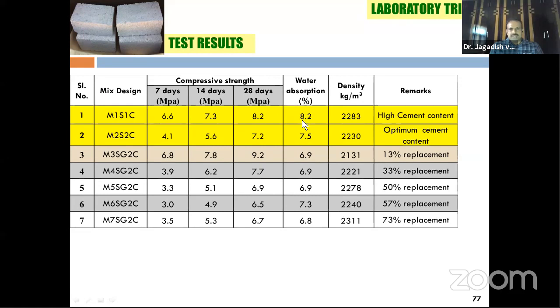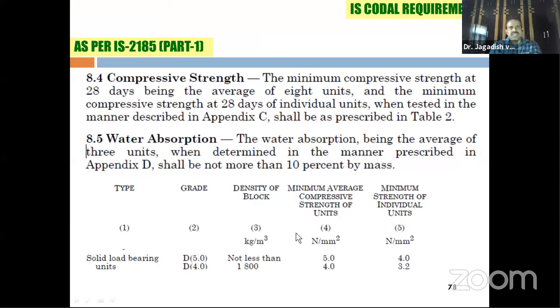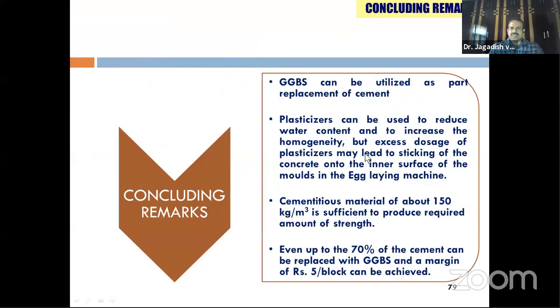Water absorption is also less than 10%. Density is more than 1,800 kg per cubic meter. And strength is also more than 5 MPa, even after replacing 70% of cement. That means 150 kg, with 70% replacement with GGBS. This is once again to remind you of compressive strength, density, and water absorption. This is about the remarks for this particular project, wherein one can use GGBS as a part replacement,